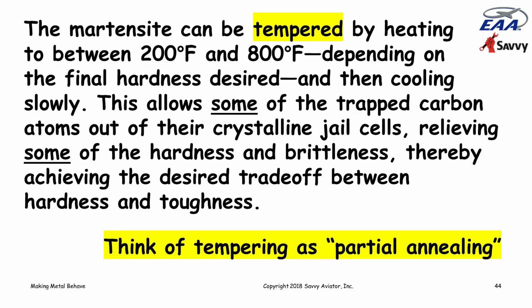You can think of tempering as partial annealing, where we do the hardening to get it extremely hard, and then we partially anneal it to soften it back to the characteristic that we want. And it's always a trade-off. The harder the metal is, the more brittle it becomes, the less tough it becomes. And so we're trying to get that magic balance between hardness and toughness that we want for a particular application.